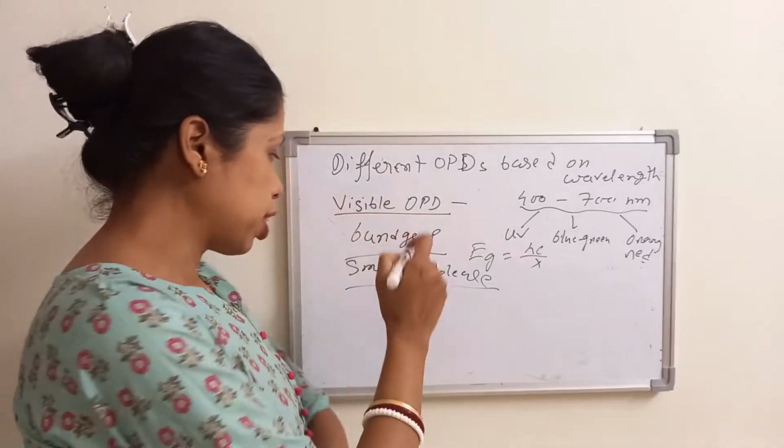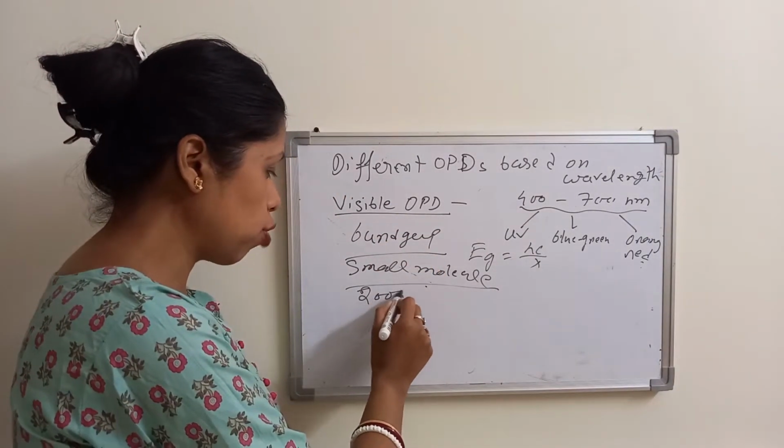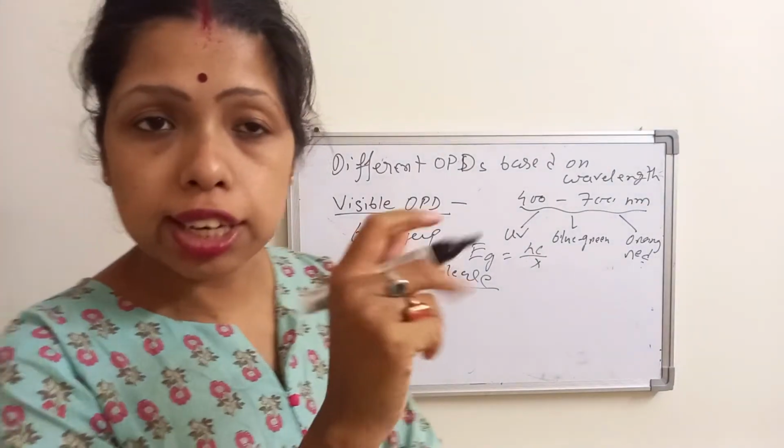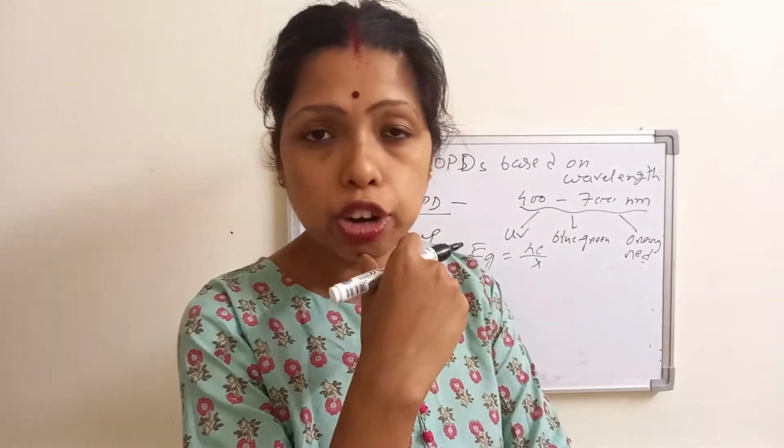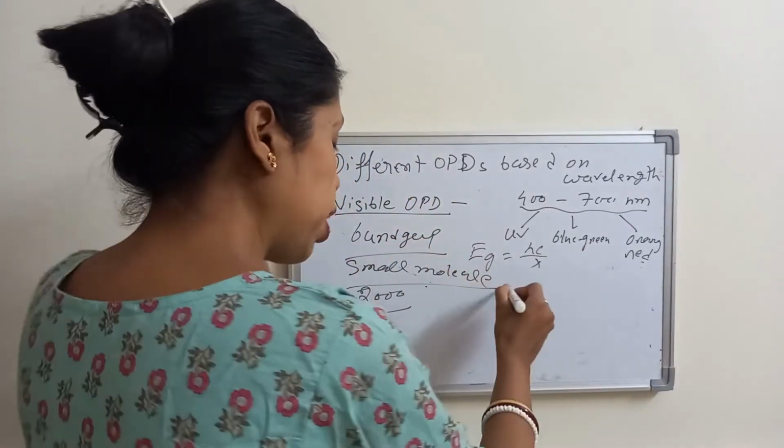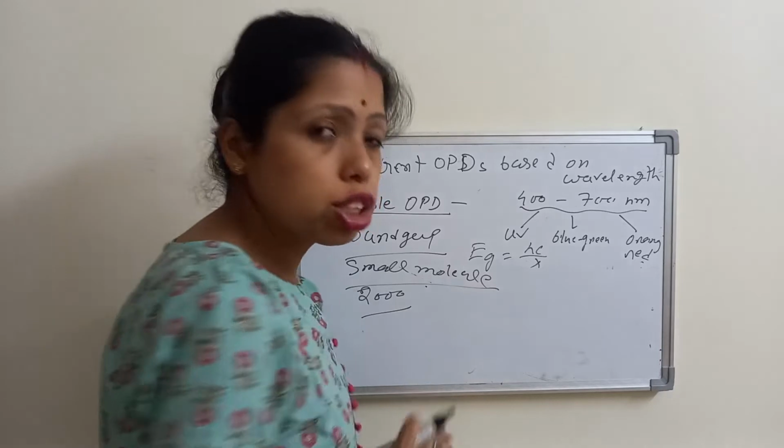Right. So one photodetector was designed in the year 2000, a small molecule based organic semiconductor photodetector, right. Why are we choosing this? Because if you choose the small molecule, it has a high degree of control of film formation. So we can design the organic photodetector using the small molecule with the help of thermal evaporation, any kind of physical vapor deposition technique. So for that we can control the thickness, and the bottom layer cannot be degraded by the upper layer, because multiple layers are required.